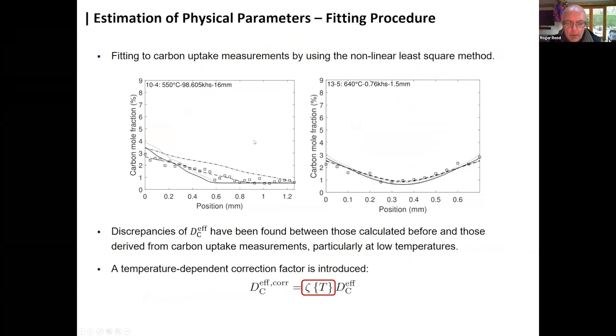We have also very carefully measured the carbon profile as a function of temperature and time. You can see typical estimates here for the enrichment, and also made measurements on unfinned tubes, where of course one can have a semi-infinite diffusion of carbon. One of the observations here actually has been that the literature values of the diffusivity we derived needed to be corrected by a small correction parameter zeta here, which is again a function of temperature, because we couldn't get the very best agreement with our experimental data by assuming values and thermodynamical assessments made in the literature.